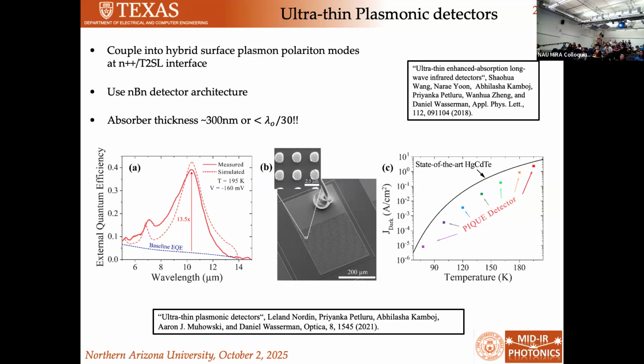This is a plasmonic detector we designed that basically has a layer of this optical metal that we grow first. And then on top of that, we grow our detector structure. We grow a very, very thin detector structure. We put a grating on it. See that here, right? That couples light into these plasmonic modes, these really tightly bound modes at the interface between our metal and our optoelectronic device architecture. And what you see is an enhancement of your absorption at 10 micron light.